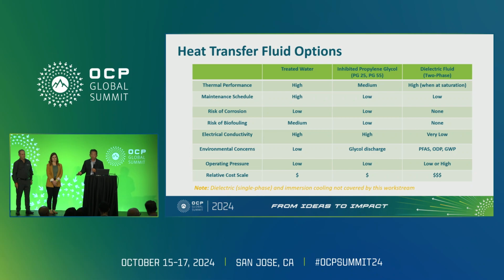This is a general discussion about how the three different coolants differ. Basically, for thermal performance, the best is dielectric fluid. For maintenance schedule, the highest is treated water, because treated water has the best heat transfer compared to PG25, but treated water tends to have biofouling. So there's a lot of maintenance in the beginning. If you keep it clean, it can run for a long time. But if you start having a biofouling issue, you have to keep adding biocide to try to mitigate the issue. That's the biggest concern. So sometimes people will try to switch from treated water to PG25 if their thermal performance allows that.